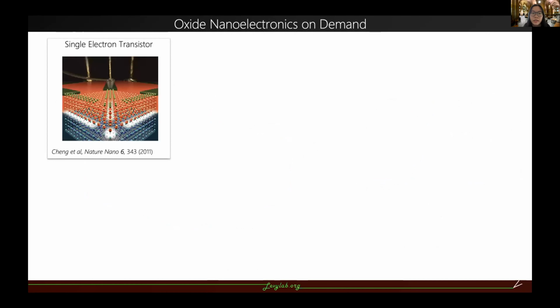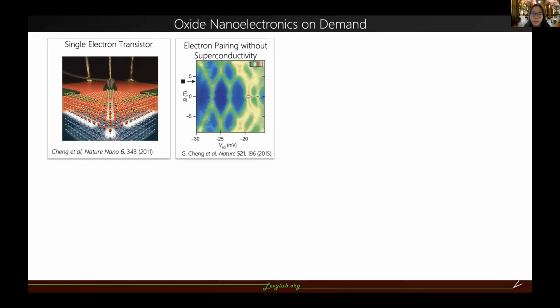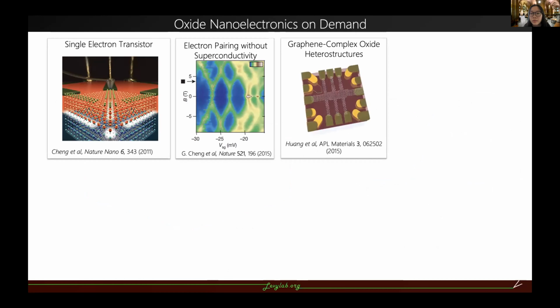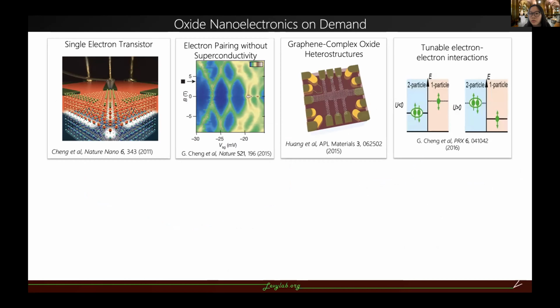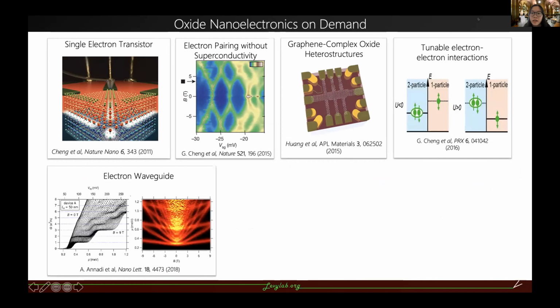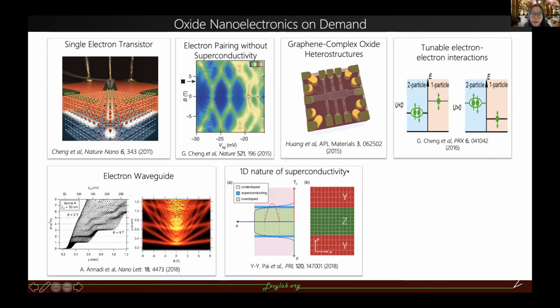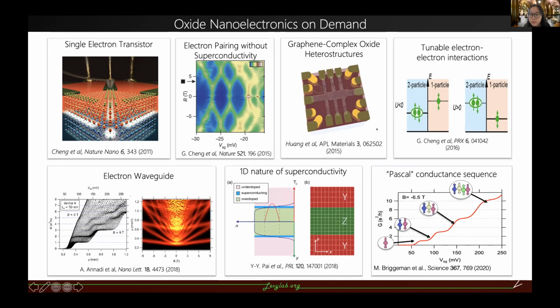So with this technique, we have created many different devices at the LAO-STO interface and explored its properties. We can make a single electron transistor at the interface, and we observe electron pairing without superconductivity. We can combine these with graphene to make graphene complex oxide heterostructures, and we also observe tunable electron-electron interactions. We have electron waveguides with ballistic nanowires, and we observed the 1D nature of superconductivity, and most recently, we observed the Pascal conductance sequence, and all of these are really good results from our group.